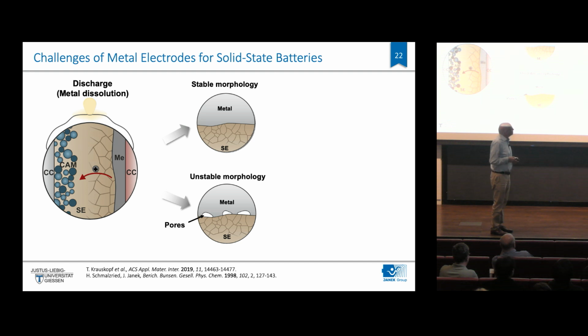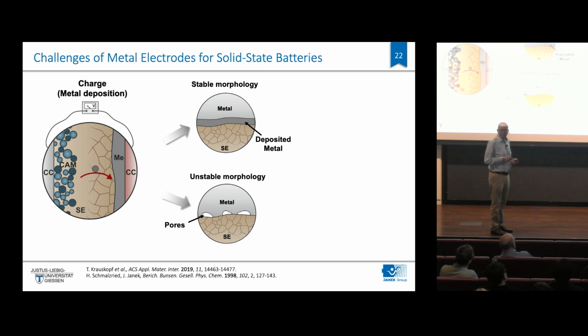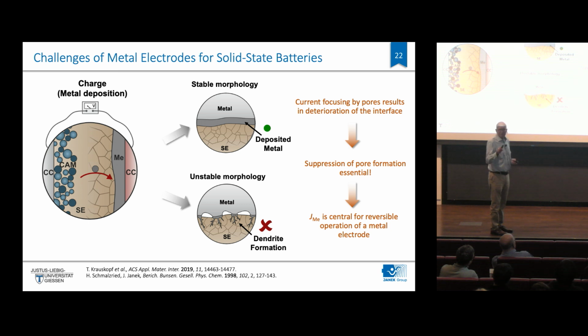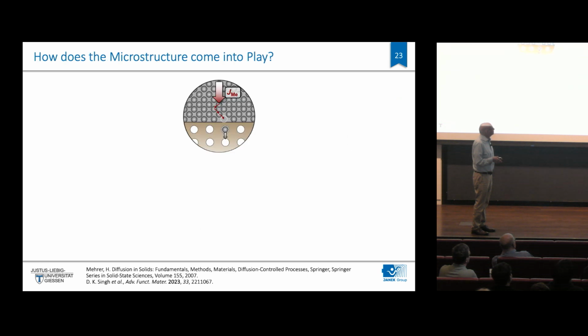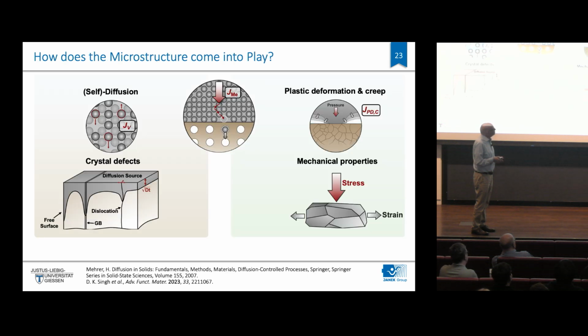Now, in the next step, if we have really our stable interface, then in fact, we can also nicely, hopefully, deposit metal then again at the whole interface. If you only have a few contact spots left after stripping, that is then typically the starting point for dendrites, because you have only a few, I would say, contact spots where the current is being strongly focused. You get constriction effects that are typical for many electrical contacts, and that is then typically the starting point for degradation of cells and of electrodes. Now, and that means, how does the microstructure then come into play? That is really the key subject.